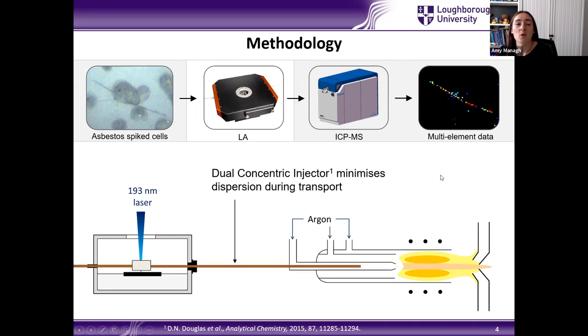Following on from that, there have also been developments in the aerosol transport as it reaches the plasma. What I'm showing on this slide is what's known as a dual concentric injector. This was something that we developed at Loughborough University. The aim of this is to minimize dispersion of that material as it passes through into the plasma. By putting our material straight through into the central channel of the plasma and sheathing it with an argon gas, we can stop this kind of turbulent mixing of the flows.